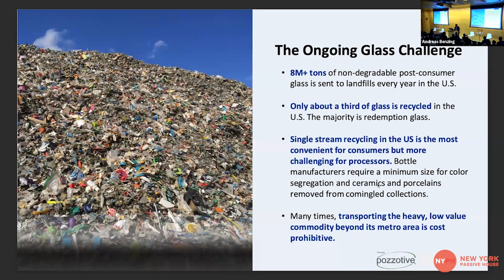And some of the challenges that we face here in the recycling industry, that's this mound of glass you see in the picture, reflects what we get in our plant. When you put your glass out on curbside, it's mixed in with paper, plastic, aluminum, and ferrous metals, and basically glass. It goes to a material recovery facility, or a MRF. Those are all regional. And then the MRF brings it to us. And basically the MRF sorts out, they do a pretty good job. They get it to about 80% glass by weight and 20% non-glass.